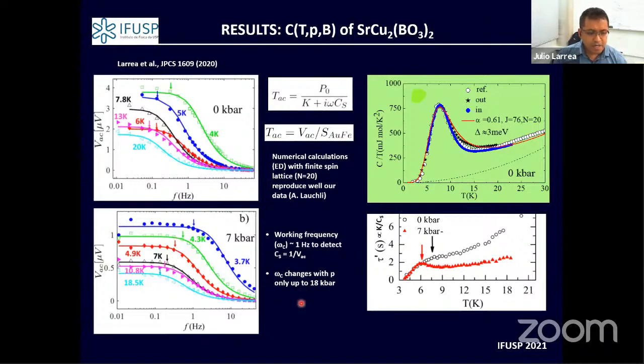In addition, we observed that this frequency dependence to maximize the specific heat becomes negligible when we measure above 18 kilobar. So above that pressure, we can in principle take the criterion of just the frequency that maximizes the specific heat and relate it directly.